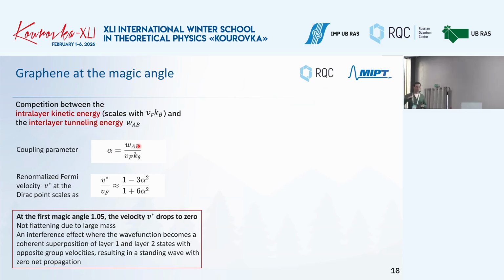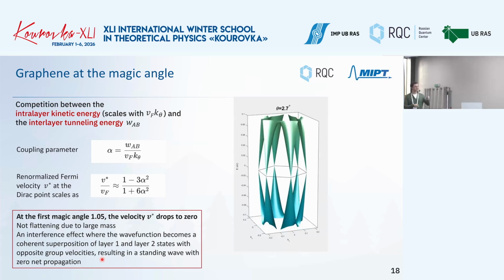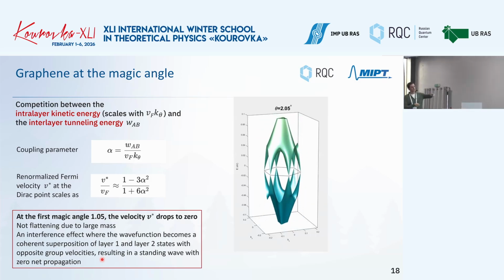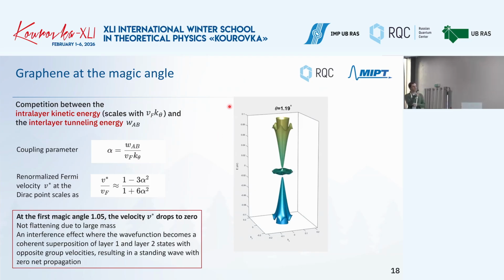And there is a flattening of the band, due to a specific interference effect, where the wave function becomes a coherent superposition of layer 1 and layer 2, and the opposite group velocities interfere, and the resulting standing wave appears, and there is no propagation. In the image, it looks like this. There is an angle changing, and you can see how the dispersion is changing. When you reach this theta angle around 1 degree, you see the flattening of the band around 0 electron volts.